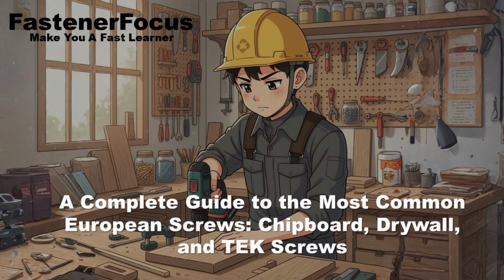The difference between a 2-year zinc-plated life and a 70-year HDG life is a matter of micrometers and temperature, all designed to resist corrosion. We introduced the concept of fatigue failure earlier, noting it as the invisible killer caused by repeated stress cycles, and we saw how thread rolling is the first defense. But the ultimate defense against fatigue failure is not inherent in the screw itself, is it? It's in how it's installed. Exactly. While corrosion is the most common visible killer, the vast majority of mechanical failures in service, particularly in dynamic systems, are actually due to fatigue. And the single most effective defense against fatigue failure is achieving the correct preload or clamping force during installation.